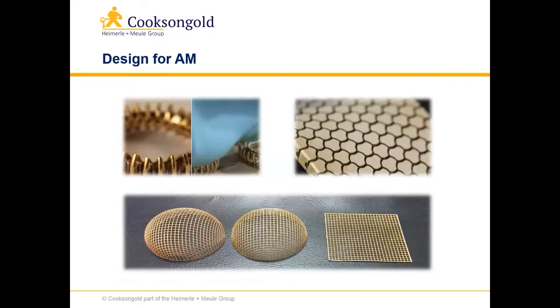So a couple more examples of some fine meshes that we can produce, and that mesh bracelet once again top right, but the one top left, probably difficult to see the image, but here we've printed an 18-karat white ring first of all, put that to one side, and then we started printing the outer cage in 18-karat yellow gold, stopped the process three-quarters of the way through again, dropped the white ring inside, and then carried on printing that cage around the white ring. Really good use of the technology.